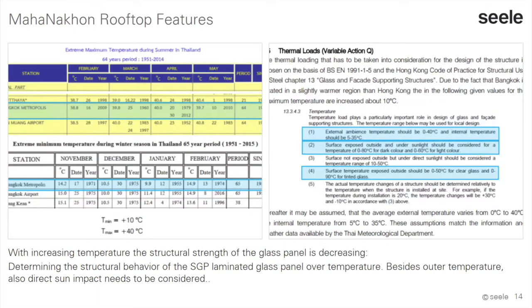So we have to keep in mind here, it's a multi-laminated glass, and with increasing temperature, the structural strength of this glass is decreasing. So how to determine the structural behavior of that SGP laminated glass panel over temperature? Now, besides the outer temperature you have in Bangkok there, it's also the direct sun impact that needs to be considered, obviously. And the direct sun impact is leading into effects like transmission, reflection, absorption, and in the end, how much of the sun energy is absorbed by the glass. So how much does the glass heat up by that?